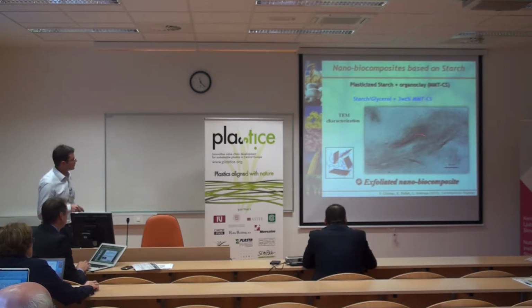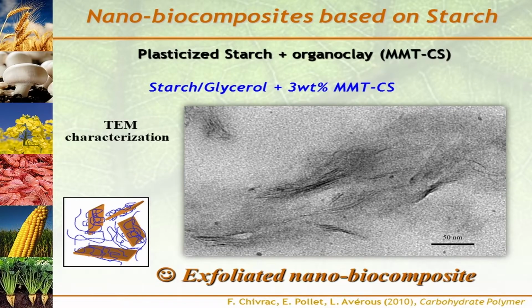Here you see the dark parts are the edges of the clay platelets, and you see that you can have individual platelets in the matrix and some stacks, but only 4 to 5 clay platelets together, whereas for the unmodified clay you have large dark areas of hundreds of clay platelets stacked together. So good dispersion and exfoliation of this organomodified clay in the plasticized starch matrix.